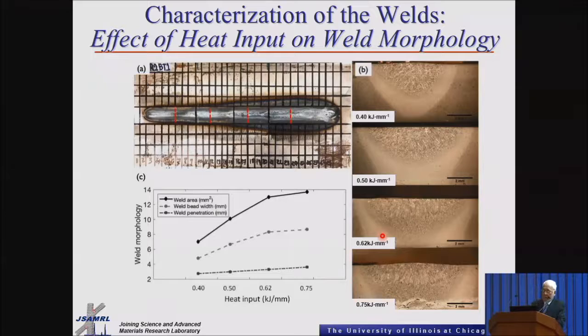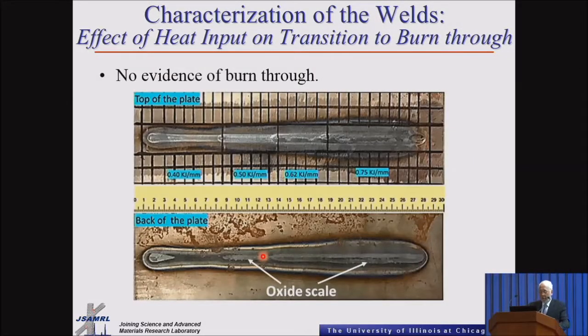All right. First of all, we wanted to do the assessment metallographically, so that, based on that, we can check against the changes in the signals from the NDE. Everybody knows this is pretty straightforward: you increase the heat input, you're going to have a larger penetration, and of course an increase in the weld area. In the next one, one other thing we want to show here: as we change the travel speed and heat input, we do not have burn through. And this is the front part of the plate.